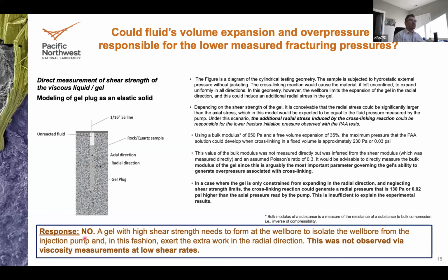Well, the response to that is no. We measure the viscosity, obviously not here, but in the rheometer, and independently of the volumes of fluids, which may affect the viscosity, and the experimental conditions, which is not in the wellbore but actually in a large vessel of 20 milliliters. Nevertheless, we measure that the bulk modulus is only 650 Pascal. And assuming a volume expansion of 35%, which is what we see at 200 Celsius, look at the pressure: negligible.